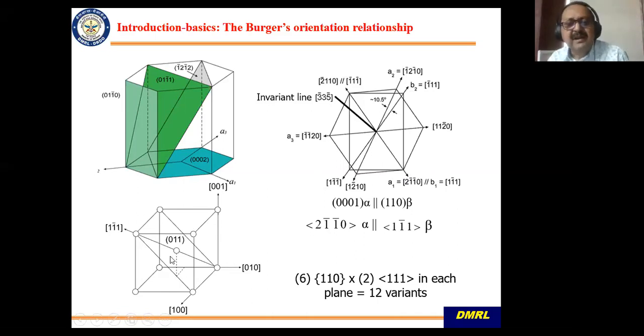So now, when you heat, let's say, Ti6Al4V to the beta region, it goes into this, and then when it transforms to alpha, each of these planes has 2 close packed directions, and you have 6 such planes. So you get 12 variants of alpha phase, and that is why you see a very geometric pattern in the microstructure also, and that is the result of this Burgers orientation relationship. The close packed direction of the HCP matches with the close packed direction of the BCC, which is this. But in only one direction, it is a perfect match. In the rest of the directions, it is slightly off, and that is how it is in titanium alloys.